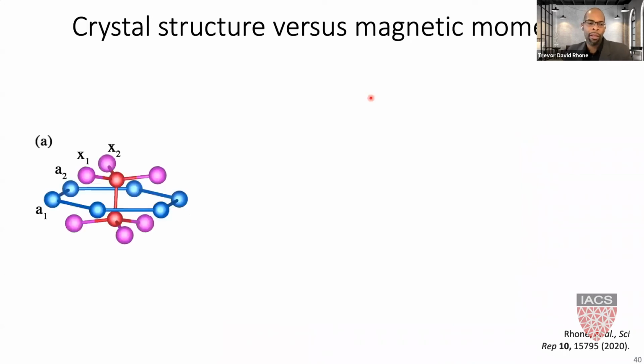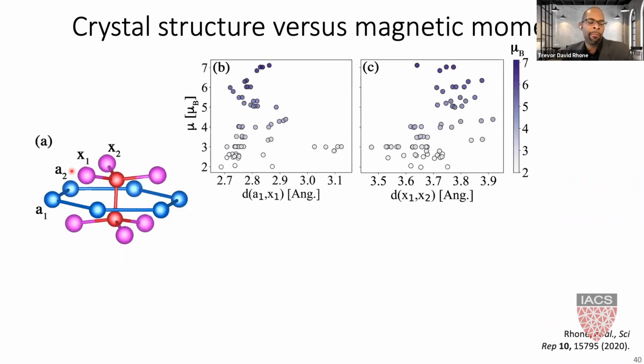We can also do a simple-minded kind of data analytics study of these materials. In particular, we can take their interatomic distances, for instance the distance between A1 and A2, A1 and X2, X1 and X2, and so on, and then plot that distance against the magnetic moment. What about the structure affects the magnetic moment? That's the key question here. This plot shows the A1-X1 distance plotted against the magnetic moment. We see that for some special value of the A1-X1 distance, the magnetic moment mu tends to grow large, but not for large distances or tiny distances.